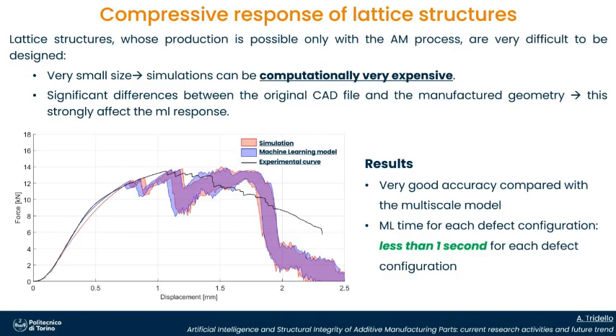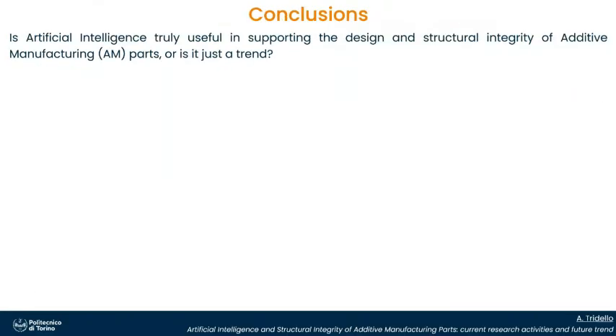And here you can see the red curves are those obtained with the simulation, and the blue ones are those obtained with machine learning. So we have a good prediction, very good accuracy, but the machine learning time for each defect configuration is less than 1 second. If we simulate it, it takes a longer time, okay?